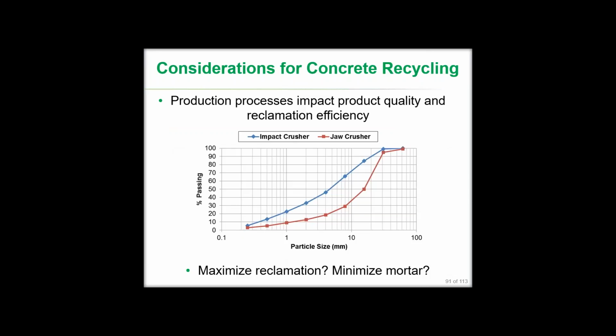You have relatively low mortar content on the coarse aggregate fraction, but you have less coarse aggregate fraction to deal with. As you can see here, you wind up with more amounts passing smaller particle sizes, so you have less coarse aggregate being produced. And the coarse aggregate is the part that we typically see the greatest demand for, the most easy use of in base applications and back into concrete materials and so forth.